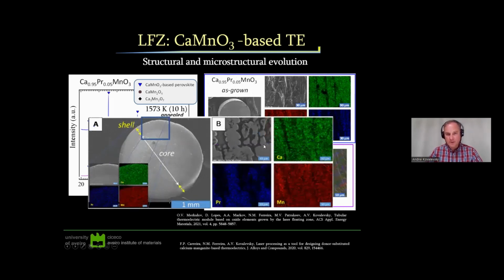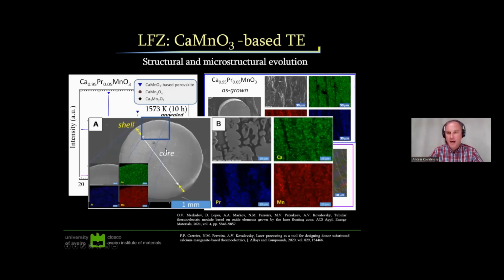We also found out that using this laser process in the case of calcium manganite-based materials, we can form some very interesting microstructures like dendrites. Dendrites are very common for laser-grown ceramics, and such core shell structures have the core and shell essentially the same chemical composition, but different electrical properties. In this case, the shell is more resistive, significantly more resistive than the core. We're trying to use this effect to find applications for sensors. So sometimes we are targeting high thermal performance, but eventually we get features which can be really interesting for other applications.